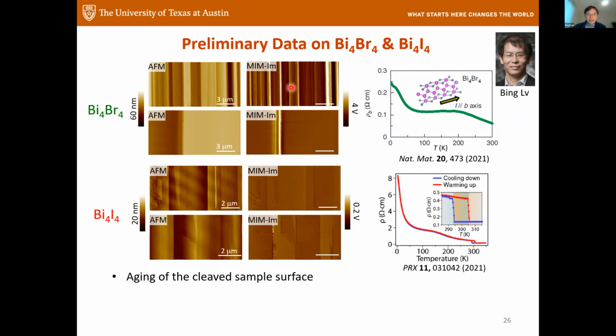So there are many things we're planning to do. So first of all, these were taken at room temperature, ambient, and we already observe, even if we just scan this, let's say 24 hours, the signal gradually decreases. So the material, these freshly exposed edges, definitely is aging under the usual atmosphere. So we will do it in vacuum pretty soon. Right, so that's the first step.